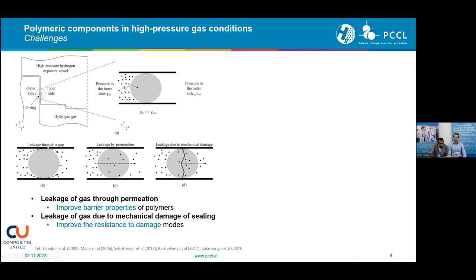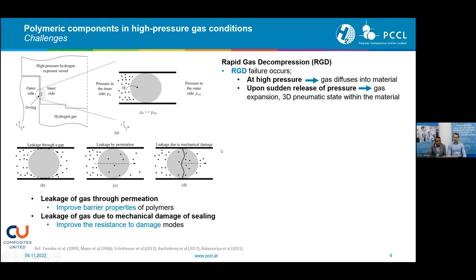Like leakage through the gap, as you see here, if we don't choose the right sealing, or the sealing dimensions are a bit different. Another method would be leakage through permeation, as you see here. This can be improved with the barrier properties of the polymer. And the other main leakage mechanism is damage, the physical damage of the sealing. So this should be improved by addressing the damage modes. So what is the main damage mode we expect here? That is rapid gas decompression failure.